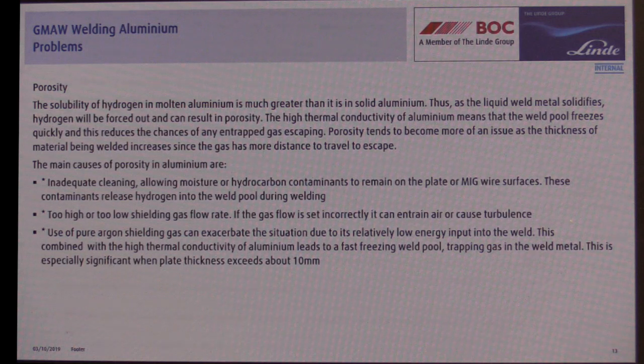Solubility of hydrogen in molten aluminium is much greater than in solid aluminium. Thus, as the liquid weld metal solidifies, hydrogen will be forced out and result in porosity, which is not something you're trying to achieve at all. Obviously, that has an effect on the strength of the material and the weld as well. The high thermal conductivity of aluminium means that the weld pool freezes quickly and reduces the chances of entrapped gas escaping.